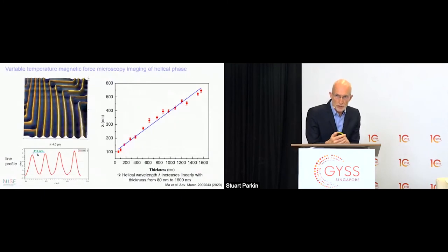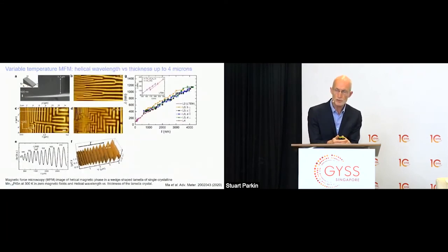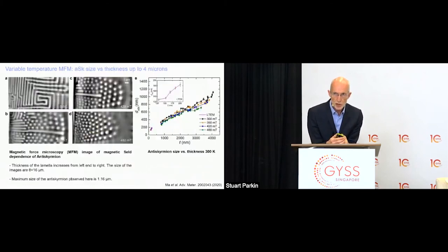And now if we switch to a different technique, we could use magnetic force microscopy to image these anti-skyrmions and helical structures in thicker lamella. We found that indeed the period of this oscillatory variation in magnetization increases monotonically with thickness, here up to 1.6 microns, and here even up to 4 microns. And you can see beautiful images of this helical structure in the magnetic force microscope. We're sensitive to the out-of-plane component. And if we change the magnetic field, you can see these white dots appearing, which are the anti-skyrmion objects.